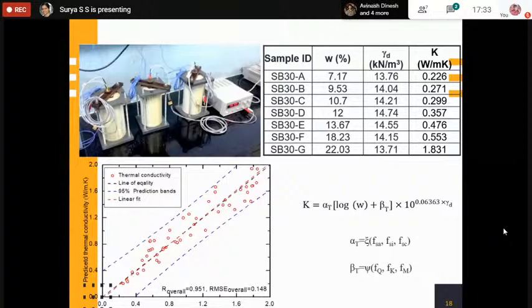And this graph shows how the model performs. So you can see the model is performing well with a regression coefficient of 0.95, and the error value is only 0.15. So like that, I could come up with a prediction model for thermal conductivity. This is about the thermal conductivity determination.